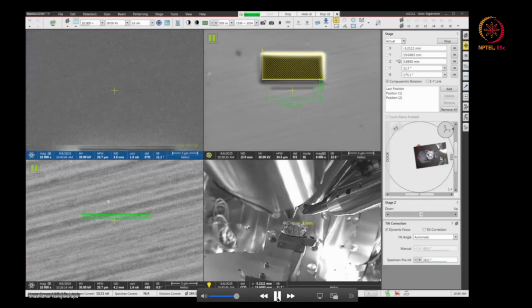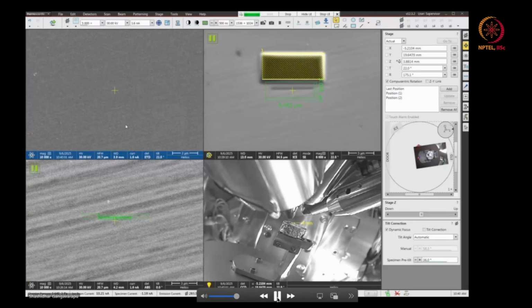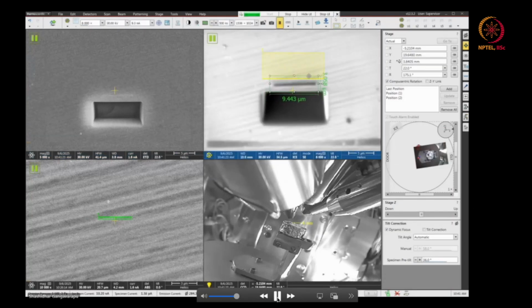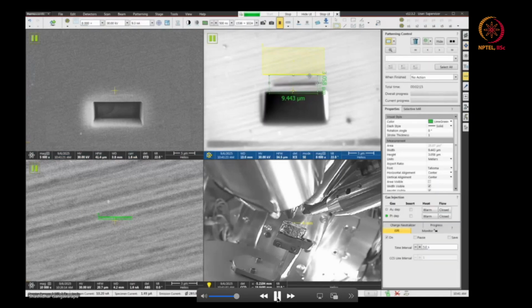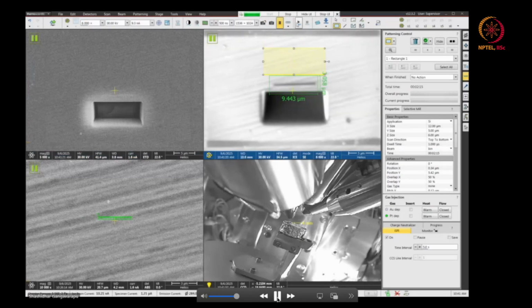Again, I have to tilt my sample to 22 degree. Yeah, the eucentric is disturbed a little bit. Then again we make it eucentric and bring our region of interest to the center. Once it's centered, we go to the I-beam window, and you can see now it is in blue condition below. It means it is in live mode, and the same rectangle pattern we will put at the top. Same dimension, application scan direction is top to bottom, and we'll start the trenching process.